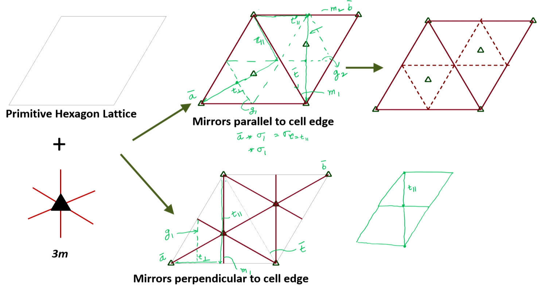I have my parallel component, which is the same as in the previous case along the mirror, and my perpendicular component comes out here, let me call that T perpendicular prime, which is just the opposite of T perpendicular, and hence the glide plane now would be parallel to the mirror at midpoint of the perpendicular component, and hence I will get a glide plane